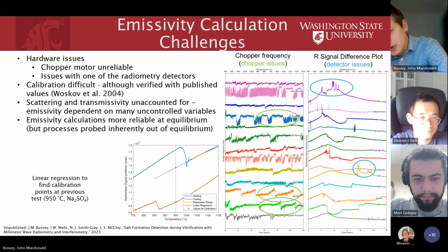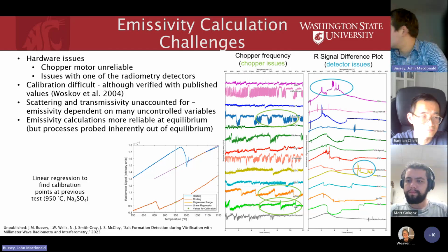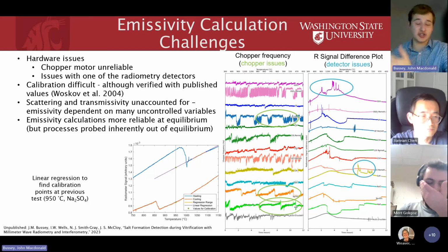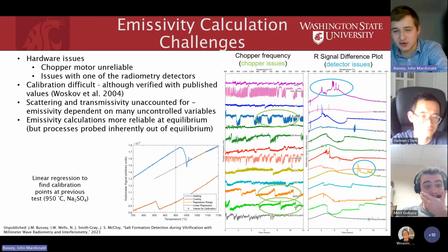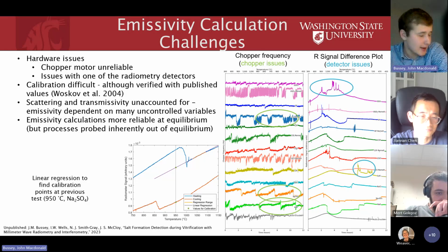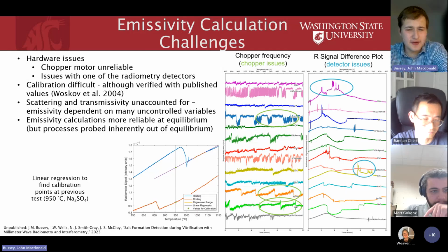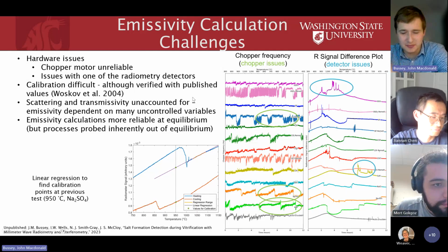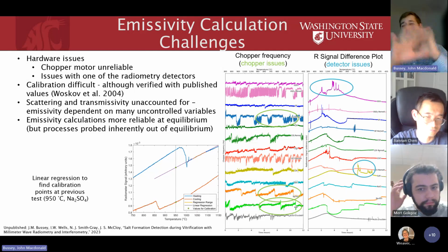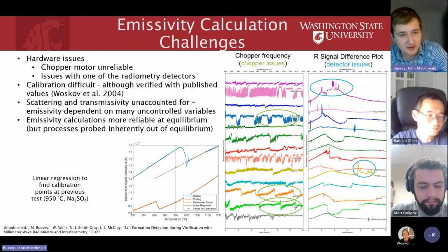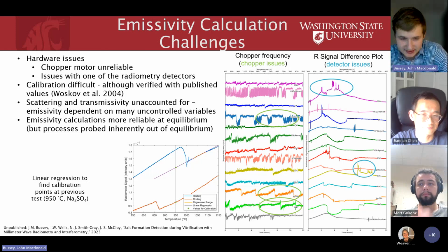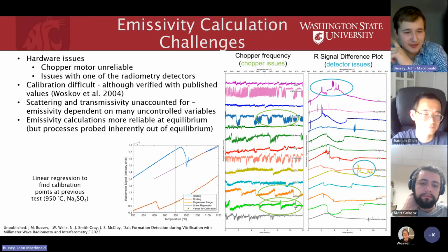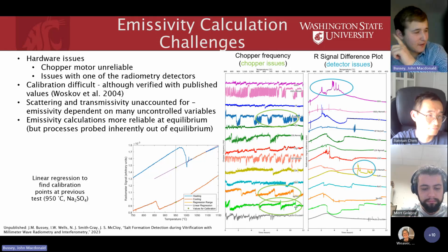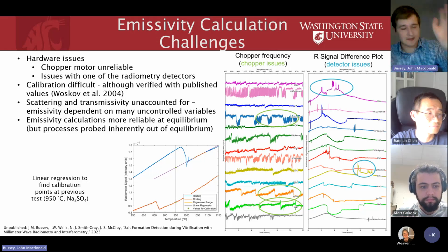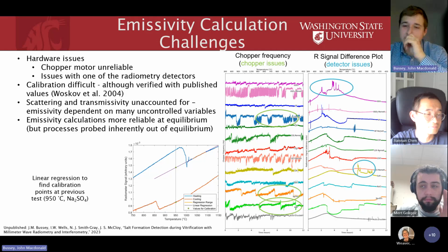So ultimately, what we want to do with this method is not just plot the radiometry signal, because that's not very physical. We want to try to extract out an apparent emissivity. However, we had quite a few issues with that, and this was not what I hoped to be presenting. I hoped to be presenting very nice, beautiful curves, but that never is really what happens in science, at least in my experience. Although actually things when I was at Vanderbilt were much more effective than most other science I've done. But that's a side note.